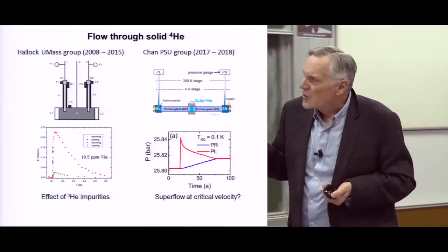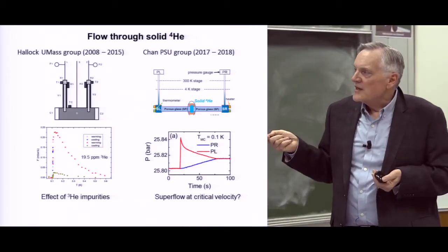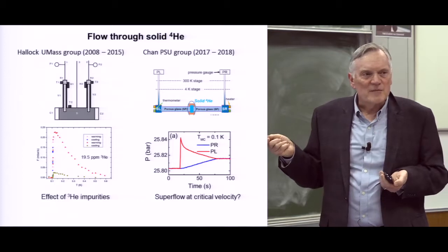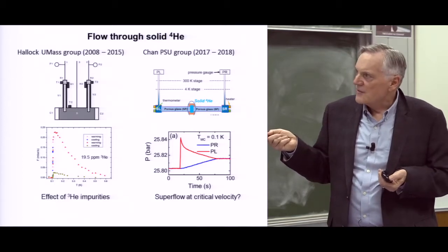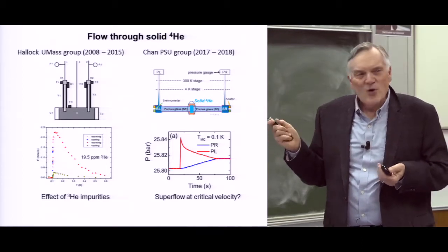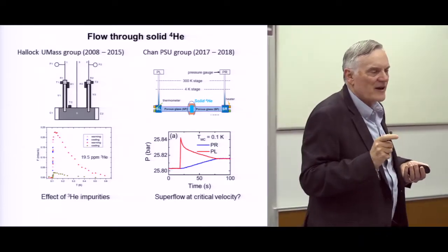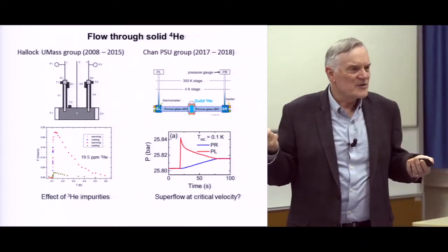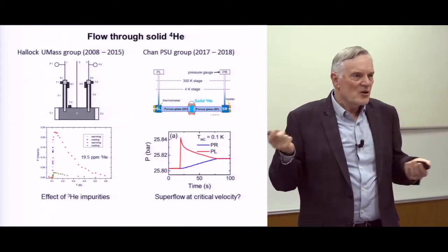And the other thing noticed by the UMass group is that it was sensitive to helium-3 impurities again. And so this is actually a plot where they found that this flow is not what you'd expect. You'd expect some kind of flow at high temperatures, like the creep we saw in crystals, but at low temperature it goes away.